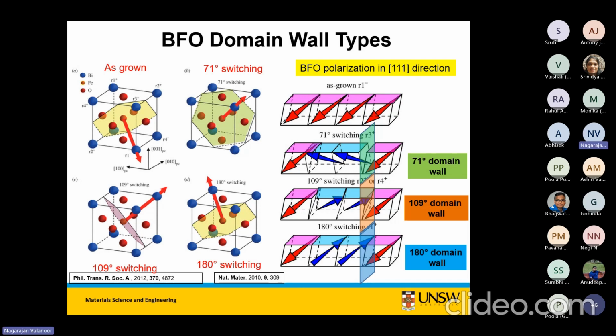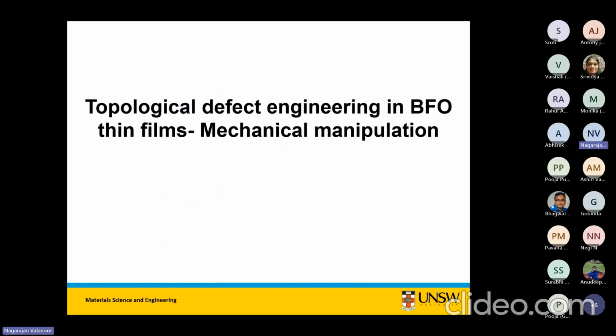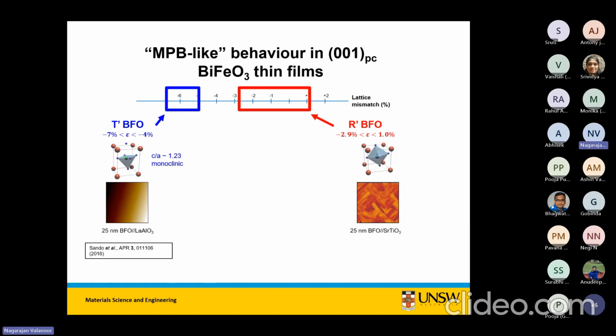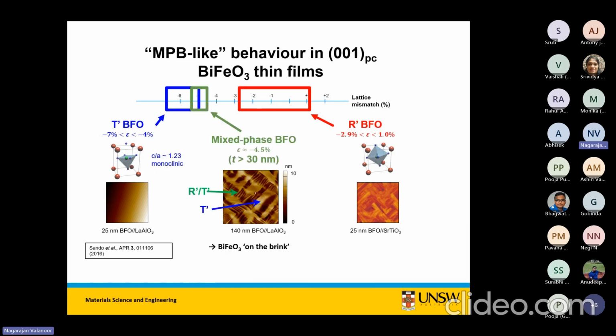Okay, so you have these different types of domain structures, but the important thing is that the polarization is tilted in BFO. It's not in its bulk state, it is a tilted polarization. It is not a normal polarization along the C-axis. So any games you play with stress or boundary conditions, you have to take into account that the polarization is already tilted. Okay. What can you do mechanically? I told you I'm going to tell you what this R phase and T phase and why LAO is. When you grow bismuth ferrite on a substrate which imposes a large compressive strain, you go through a series of crystallographic changes in the material.